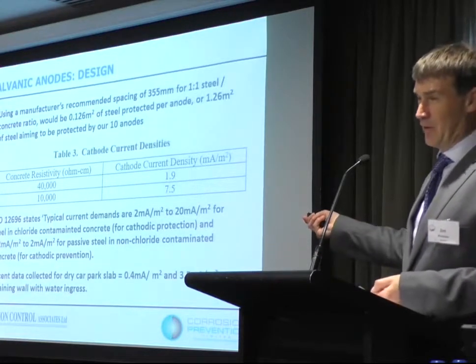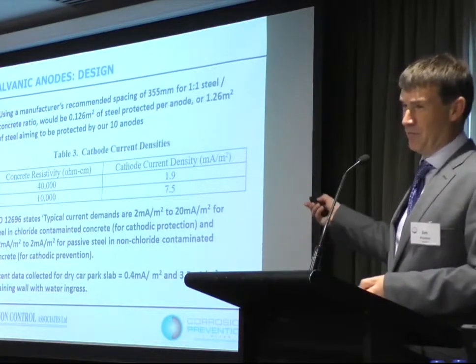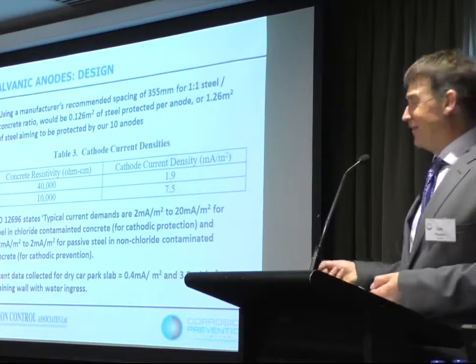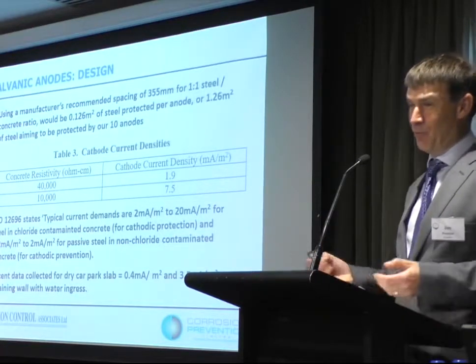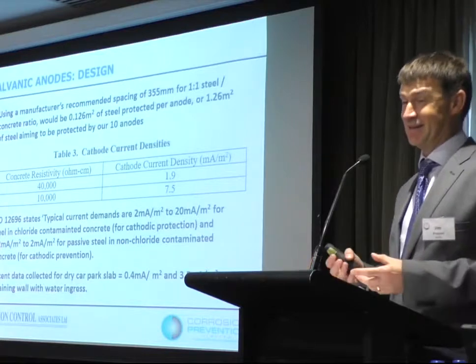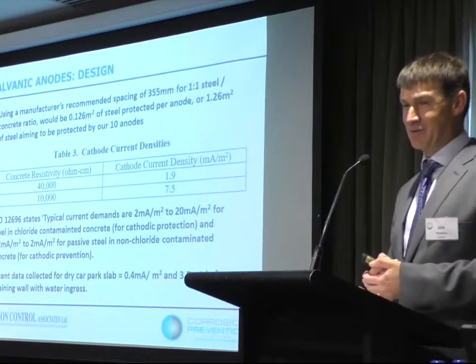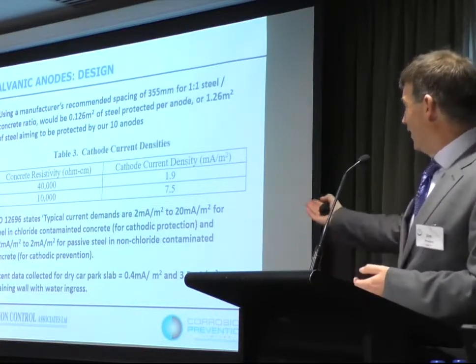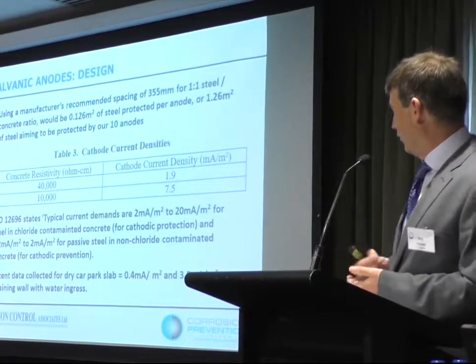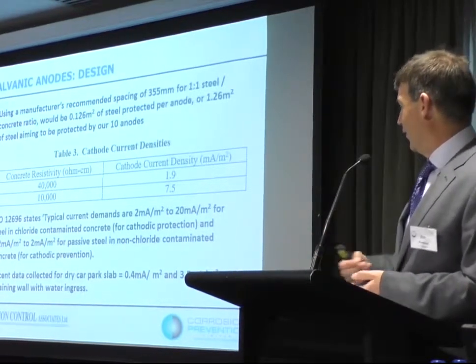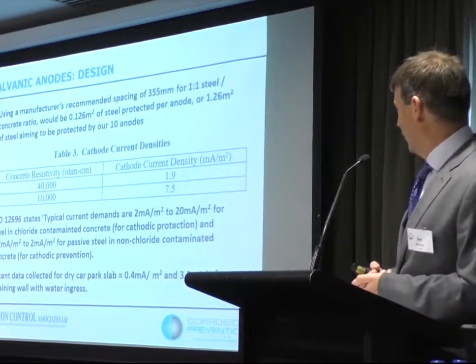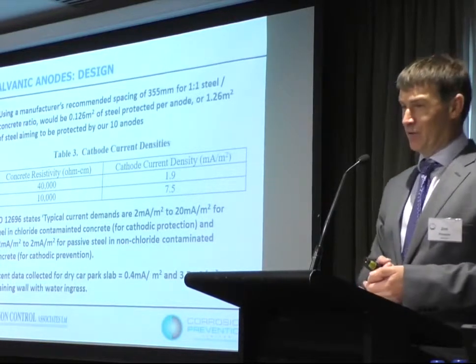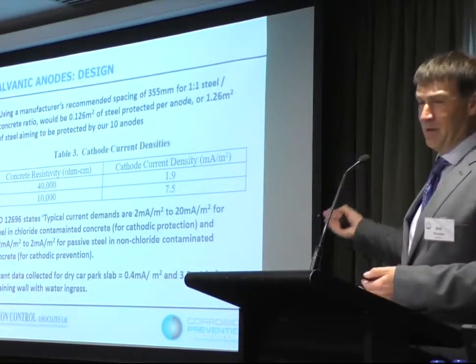We went out to a site quickly and just collected some data to see if we were somewhere in the right ballpark. And this was just a couple of data sets from when the anodes were first connected. So it's when they're giving their most output. On a dry car park slab, we got 0.4 milliamps per square meter. On a fairly damp retaining wall, we got 3.5 milliamps per square meter. So we thought, well, we're kind of in the right ballpark. We've probably been a bit generous.